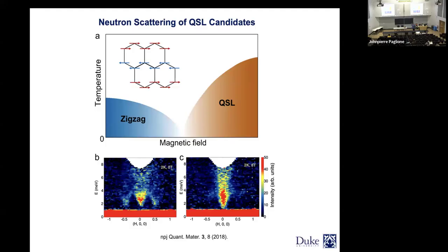In this particular case, I would also like to note that, not only site vacancies and site mixing, but also if you have a two-dimensional or quasi-two-dimensional system, the way that these layers are sitting on top of each other, if they have some sort of an angle, a stacking fault, it is called, that can also induce something related to what we think a quantum spin liquid can show. And for this ruthenium trichloride, there is this stacking fault, unfortunately, so it complicates the picture a little bit more. Okay?